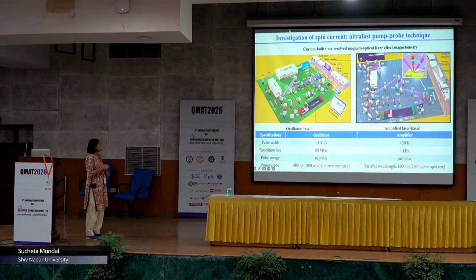So, this is a Ti-sapphire laser based oscillator cavity, which can emit a fundamental of around 800 nanometer. Then that fundamental is split into two. One part is being frequency doubled, which is appearing as the violet light. Another is the probe, which is time delayed with this delay stage, and then the time difference between the pump and probe is varied to get a time dependent signal.